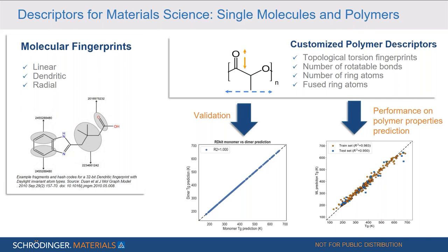Moreover, there are other factors which strongly influence the morphology and therefore the properties of the polymer, for instance, the stiffness. So the customized polymer descriptors also take into account the number of rotatable bonds, for instance, and also the number of fused ring atoms, which has a strong effect. So if we had a lot of fused ring atoms, we would increase the stiffness of the polymer, and this would then also strongly affect the properties.